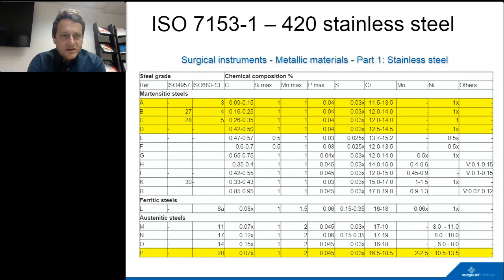So let's have a look at the composition of the steel here. We have the top four yellow highlighted lines that I've flagged up there are generally the most popular, actually probably B, C and D. What you'll see that's a bit different about them each is that the carbon level, which is C, increases as we go down. And that is because an instrument that's made out of a D needs to be a lot harder than an instrument that's made out of a B.